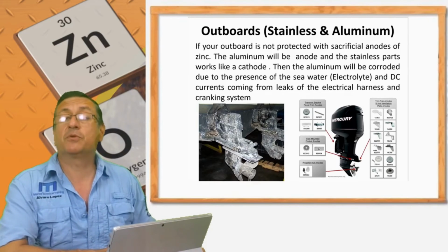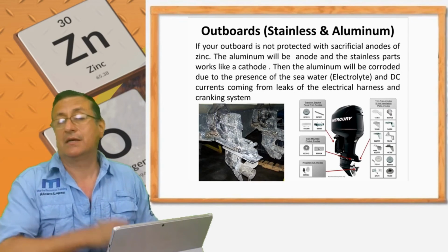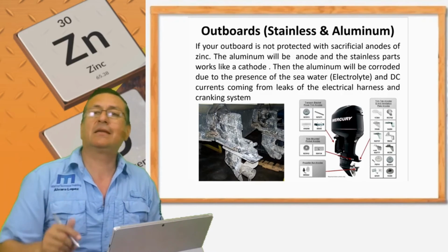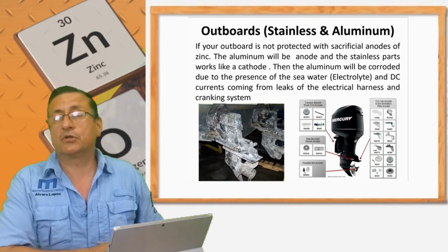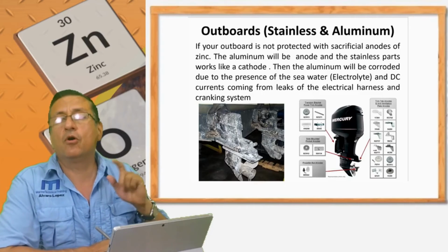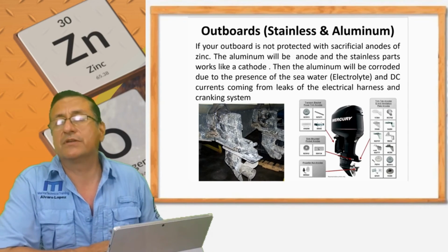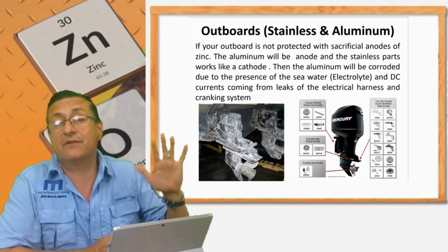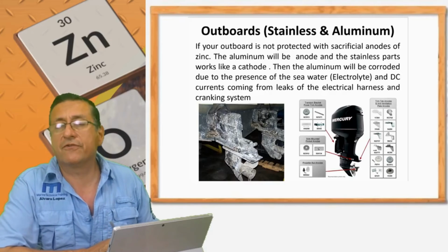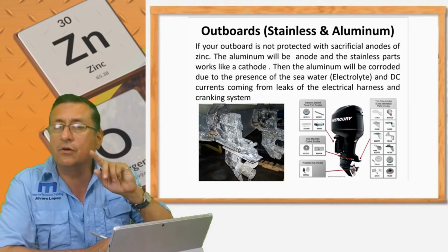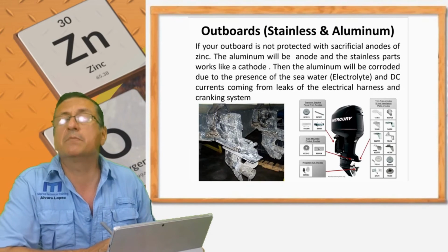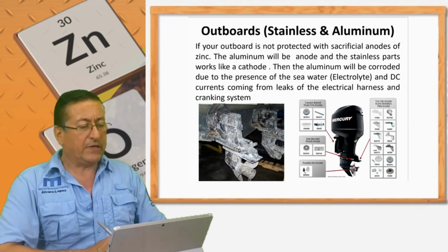Yeah, for that reason you need protection with the zincs. The zinc absorbs the oxygen attack, and the aluminum will be protected. The sacrificial anodes are mandatory, my friend. This is the only way to protect other metal: with sacrificial anodes. What is the best of the sacrificial anodes? It is the zinc. Magnesium also is good, especially in fresh water. And some aluminum alloys, we are going to talk later about that, are good in some specific situations, especially in brackish water. Okay, my friends.